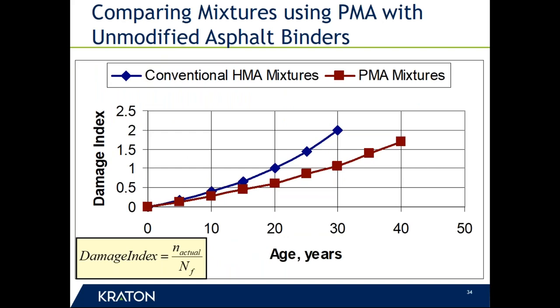What they ultimately developed on this was a damage index, and so they were able to come up with that for conventional mixes and polymer modified mixes. Again, these are for paired sections that they're looking at, so it enables a direct comparison. And what you see here is about a 50% improvement in the anticipated life. So if you're looking for ways of enhancing the life of asphalt pavements, this is clearly one way of doing it. This is why we've seen polymer modified binders become so much more popular in recent years.